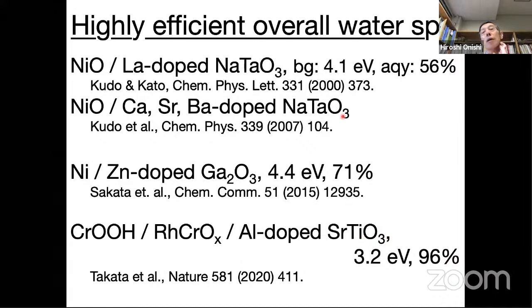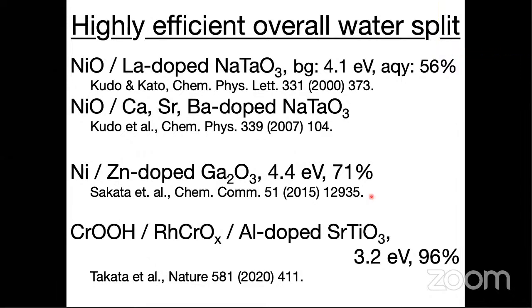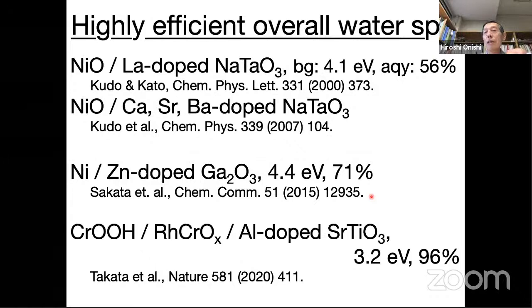These materials are always wide band gap. So we need ultraviolet light to excite these photocatalysts to make hydrogen from water. Strontium titanate, gallium oxide, and sodium tantalate. Always we need an ultraviolet light. So this is the reason why by using these materials, we cannot produce hydrogen from solar light. The ultraviolet light in the solar radiation is very limited. A very small amount of ultraviolet light is available on the surface of this planet.